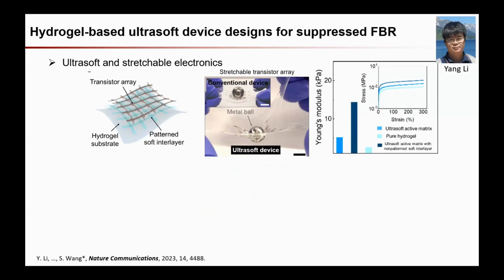Okay, so this shows the importance of achieving very low modulus for the electronic layers in the device. Besides the material work, we have also spent some effort creating a full device design that can be compatible and have low modulus. In this work, my student Yang has been able to show that if we introduce only a very soft interlayer between a still relatively rigid functional layer at the surface and a very soft hydrogel substrate, he can achieve a very low modulus for the overall device, as shown here, similar to the hydrogel.